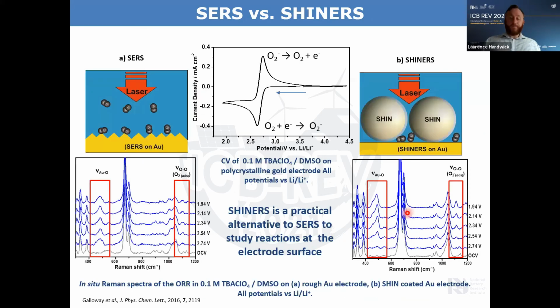I'm going to show now an example where we've used these SHINERS particles to investigate the formation of superoxide. If you remember back where I showed all the reactions happening to form in a lithium air battery, this is the first step of adding an electron to oxygen. Here we have our cyclic voltammogram where we're sweeping the potential to lower potentials, and we get to a point where the electron is transferred and oxygen is reacting to form the superoxide. And as we sweep back, we can see the reverse reaction where we're oxidizing the superoxide back to oxygen and the electron.